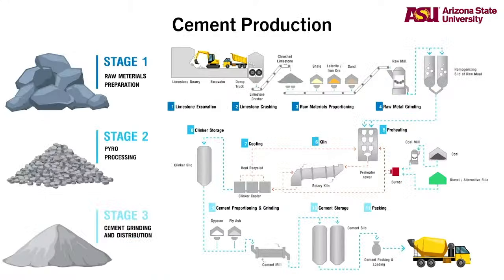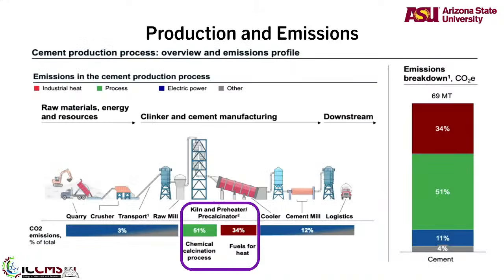So cement production, again, I'm not going to go through it. I'm preaching to the choir. You have to extract raw materials. They have to go through a whole sequence of grinding, crushing, pyroprocessing, packaging, transporting, and it adds up with respect to carbon impact. But if you look at where the most impact comes from, that's in this manufacturing step, where you take limestone, you heat limestone to 900 degrees Celsius to make it calcium oxide, and then you fuse the calcium oxide with silica and alumina to form what you get as clinker, and then you grind the clinker to get cement. That process of calcination, where you heat the raw materials and then fuse with silica and alumina, that's where the highest amount of carbon and energy impacts are.